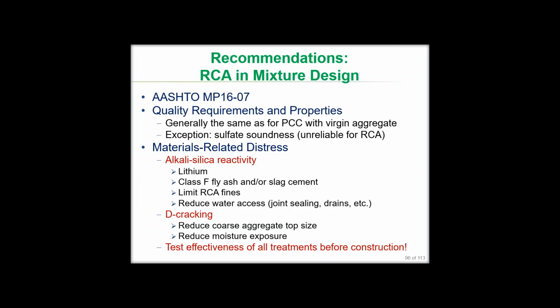The only real exception, the significant exception, is sulfate soundness tends to be a relatively unreliable test for crushed concrete. The numbers that you get do not indicate the potential freeze-thaw durability of that material. So that test is generally dismissed, and if you want to evaluate the freeze-thaw durability of a recycled concrete aggregate, there has been some work done now with the hydraulic fracture test in Indiana, and then just standard ASTM C666 or the equivalent AASHTO test can also be used.